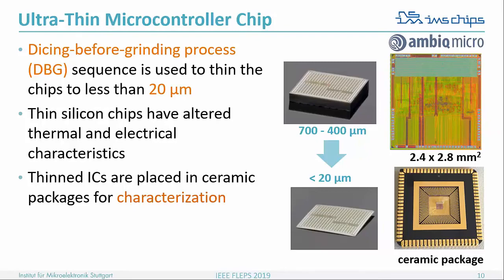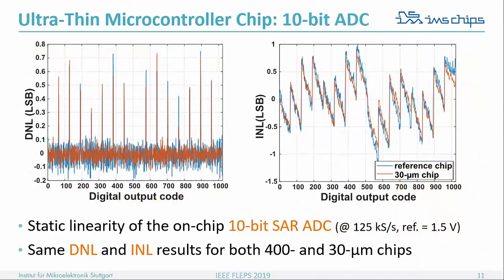So the first effect is that we characterized the 10-bit ADC on board. It's a successive approximation ADC on board, and we have recognized that the accuracy of the ADC in terms of linearity, DNL and INL, so differential and integral nonlinearity, was not affected by chip thinning. And of course, we will need to consider also bending, so further tests could be done when bent, but we need to adjust the setup so that we do not affect the linearity by the measurement setup.